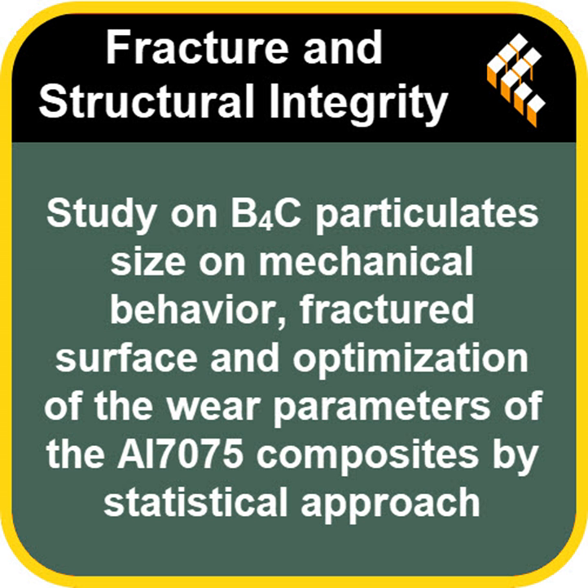Okay. And how did speed and distance affect friction? Was it complex like the wear rate? A little less surprising here. The COF decreased with increasing sliding speed. Why is that? That's likely due to the heat generated at the contact point. Higher speed means more heat, which can slightly soften the very surface layer of the material, making it easier to slide over, like putting skis on warmer snow.